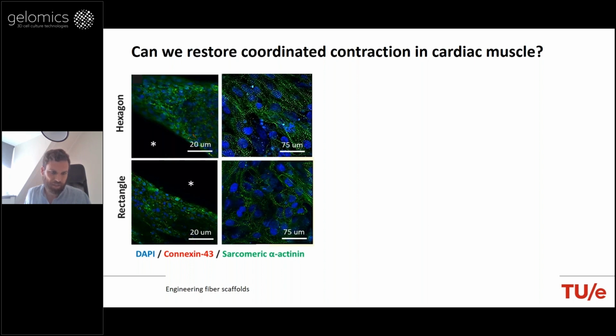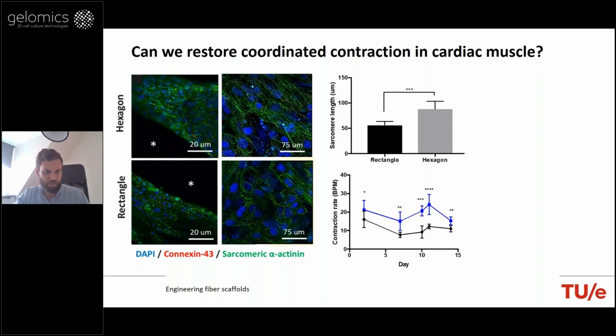Then we compared the cells cultured in the two geometries. We also went further on quantifying the sarcomere length. And I think it's clear from the confocal images that in the rectangular constructs, the cells were more disorganized, while in hexagons, they were more organized towards one preferential direction of the hexagons. And I should mention here that we were not printing perfect hexagons. We are printing more deformed hexagons that show the chain link type of organization, and that, of course, induced the alignment. So the sarcomere length was longer in the hexagons. They were more aligned. As a functional parameter, we quantified the contraction rate, and we observed that in blue, the contraction rate of the hexagonal shaped patches was higher. So the synchronous contraction of the cells, so they were able to couple and contract in a synchronous way, was higher in the hexagonal constructs.